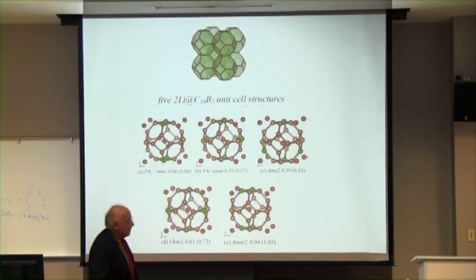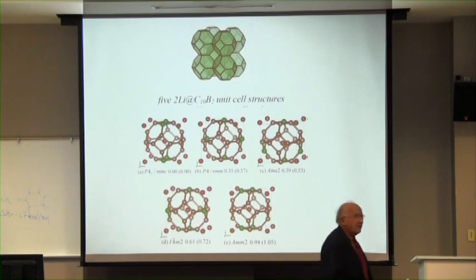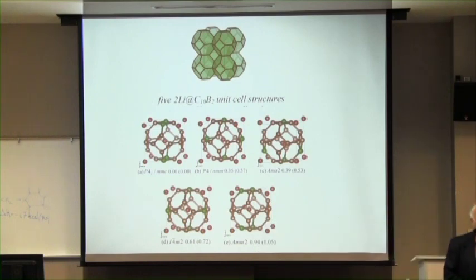And here, I tell you, you can't get away from isomerism. It's the most chemical thing, and it's everywhere you look. You saw it in the benzene nanothreads. I had many isomers. Where's the isomerism here? In the sodalite cage, the simple one, I put 2 lithiums inside the cages, and then I've got to put 2 borons outside. But there are 12 carbons in the unit cell, so I've got to replace 2 of the carbons with borons. There turn out to be 5 ways to do this. This is isomerism again. Now, that's easy.